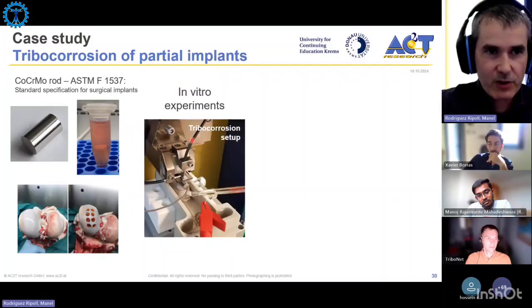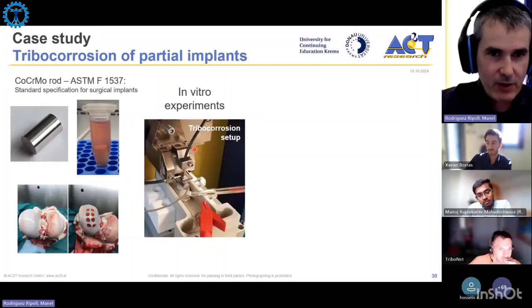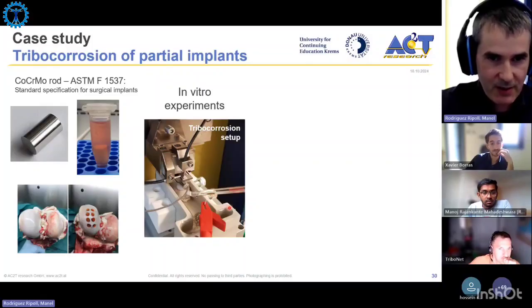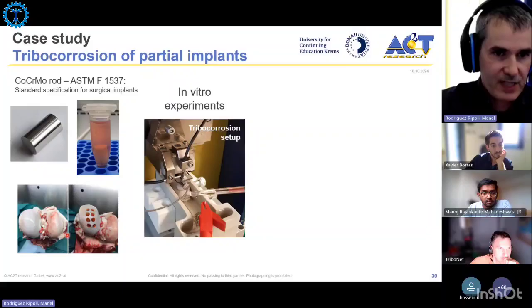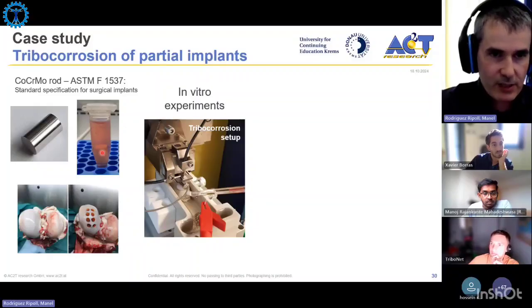And what we did here was in vitro experiments, quite challenging. So we were having not only the mechanical wear under control, the electrochemical conditions were also kept under control, but also the biological. So we were having live samples from a bovine that were immersed in this solution, that contains nutrients, contains antibiotics to ensure that the cartilage is alive. So we can keep the cartilage alive for a couple of days.